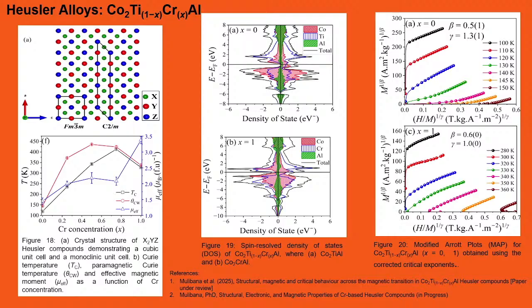Remember, my resistivity curves went flat like this. In this case, the resistivity curve starts to turn up, suggesting there's another mechanism driving most of the electrons of the current flow. So we added chrome to the system. Interesting. And what the chrome does as we add this is actually you lose this